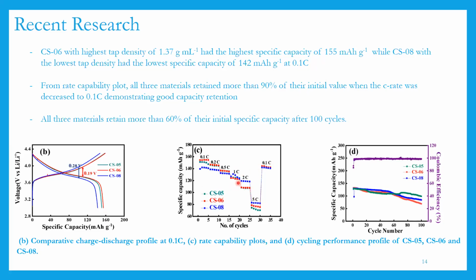And so which brings to the second plot, which is a rate capability plot. And this will help us, first of all, see how each material performs at the different C rates. But then also when we charge it back up to the lowest C rate, does it retain most of its initial specific capacity? And we found that all 3 samples retain 90% of the initial specific capacity once we charge it back up to the lowest C rate, which was good. And then the final plot looks at the cycle stability of these 3 materials. So we cycled these materials at a C rate of 1C for 100 cycles. And from this data, we were able to find that all 3 samples retained 60% of the initial specific capacity after 100 cycles, which is good.